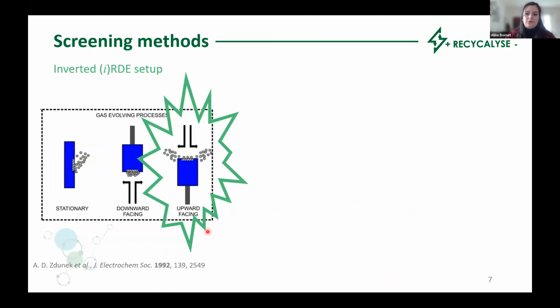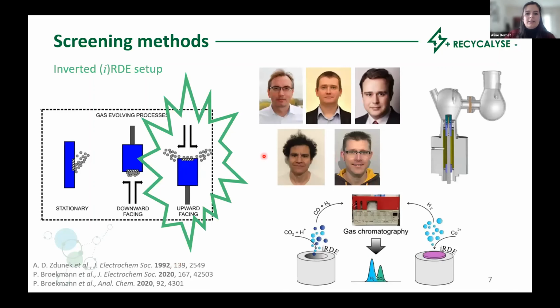A simple and elegant solution to solve this buoyancy problem is to rotate the setup by 180 degrees. With this upward facing configuration, the formed bubbles can finally escape the catalyst surface and reach the electrolyte surface. This was actually proposed 30 years ago, but never really implemented for gas evolving processes due to technical challenges. Until these guys from the Broekmann group, also at the University of Bern, designed this so-called inverted RDE. The novelty of their setup is that it is hermetically sealed, and so it was possible for them to couple it to an online gas chromatograph, and so directly analyze the gaseous product.